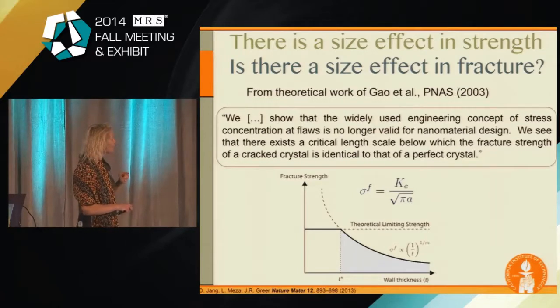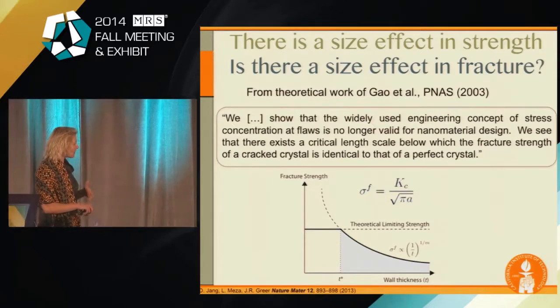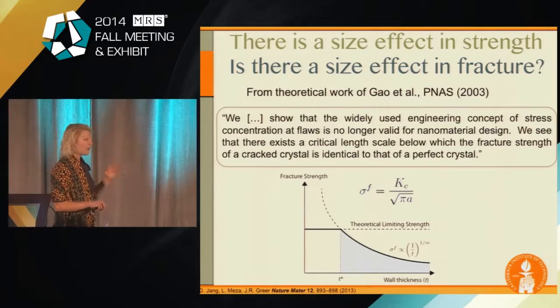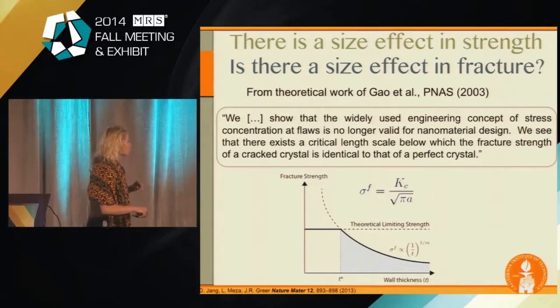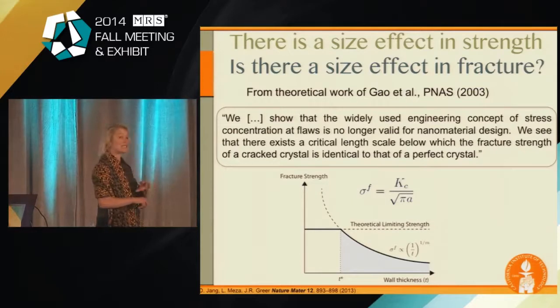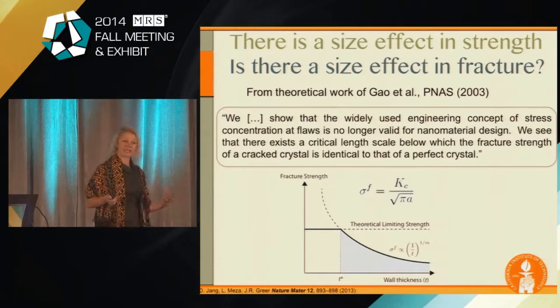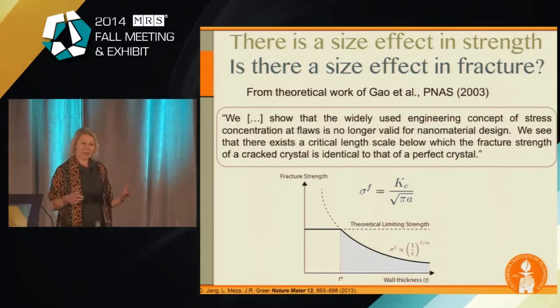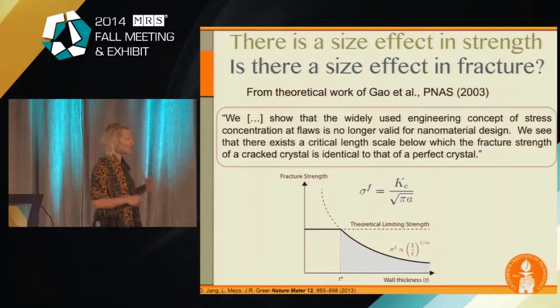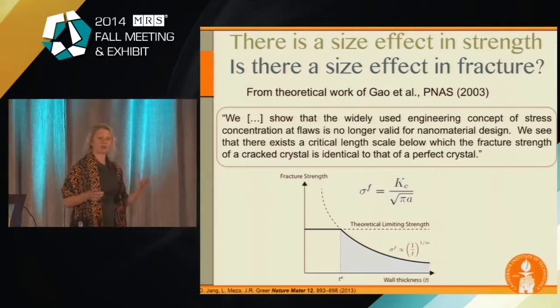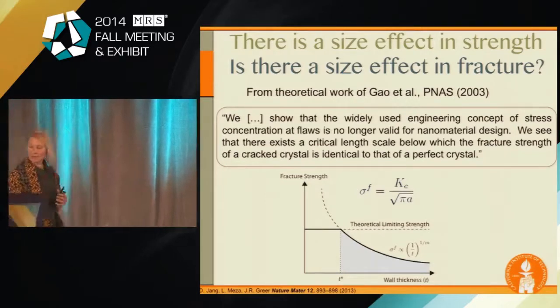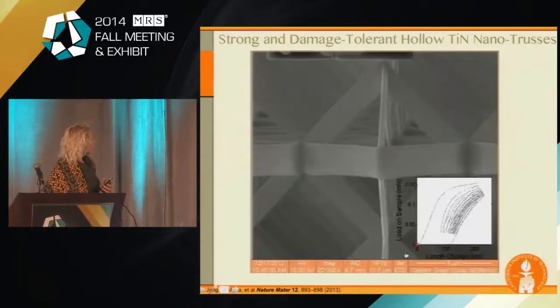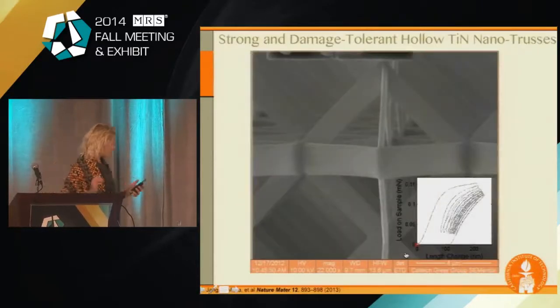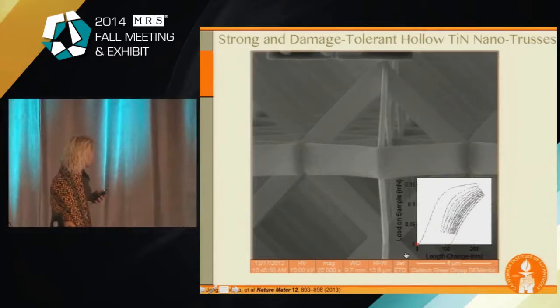And this is a big question because there was a theoretical work by Huajian Gao that was done about a decade ago, which showed that at some critical length scale, the strength of the materials, or rather the fracture strength of the materials, shifts into this regime where it's independent of the flaw size. And in a way, one may interpret that as materials become insensitive to flaws. So when you get to be sufficiently nano, this theory predicts that you will no longer suffer from flaws. You can make ideal materials. And so at the time when we did this work, this was my former postdoc, Dongchen Zheng, who is now a faculty member at KAIST. He did this experiment.